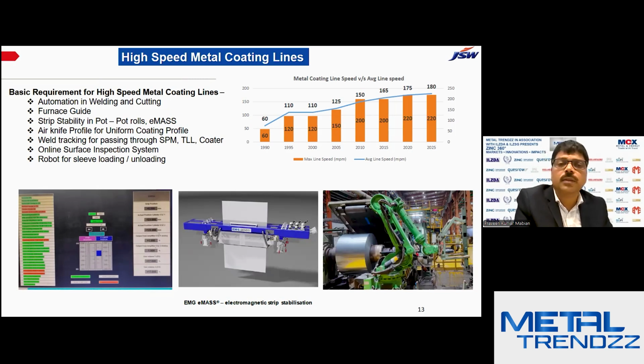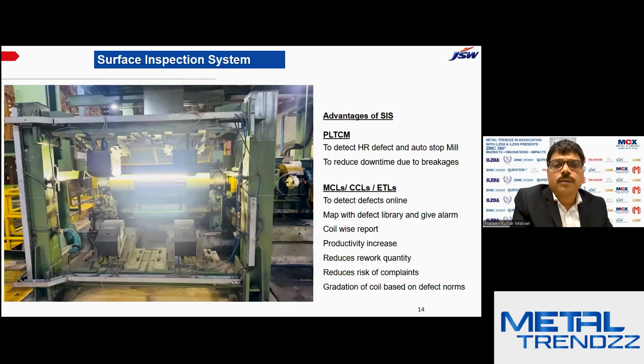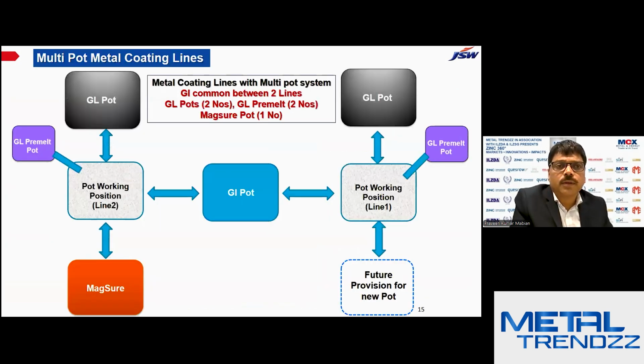So surface inspection is one thing, because at high speed it's very difficult to identify the defects. So unless you have a very good surface inspection system, it will be very difficult to identify the defect. So not compromising on the yield part, you can always increase the speed if you have a very good surface inspection system. This is a snapshot of the surface inspection system that we have.